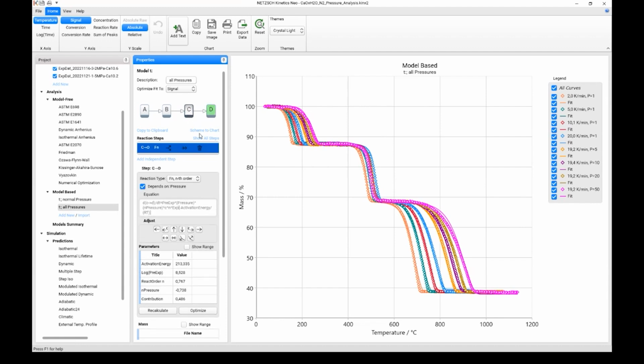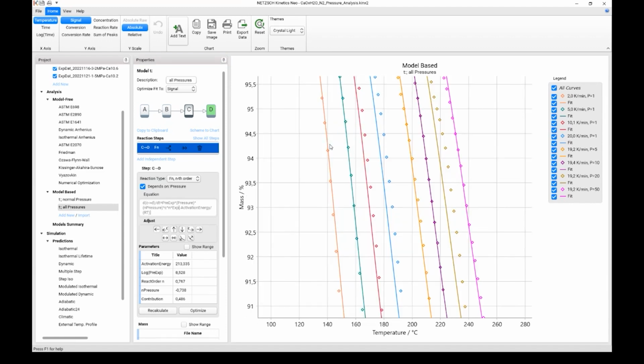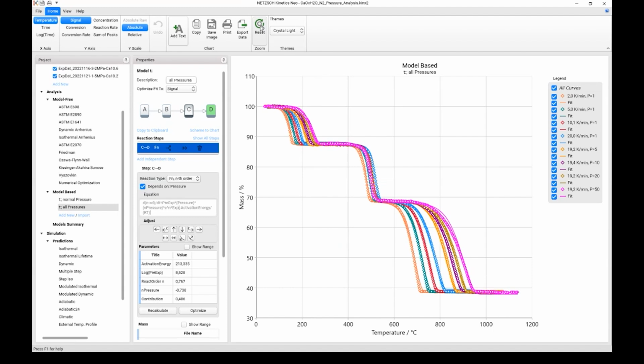And for the last step, C goes to D, again we have dependence on the pressure, because here we have a reversible reaction and the pressure has an influence on the reversible reaction. And again, here we see that there is a good fit for all data for different heating rates and for the data which are measured at different pressures. And it means that here we can take this model and make predictions for other temperatures and for other pressures and see what the kinetics of our process will be.